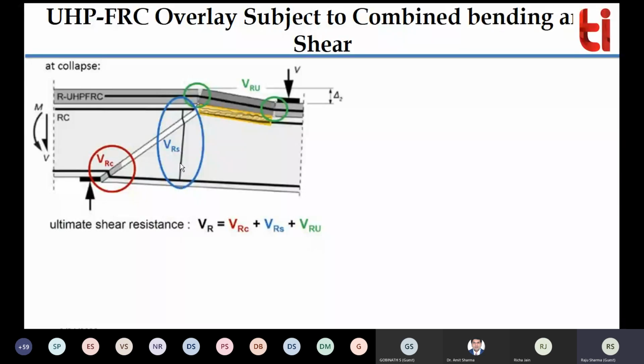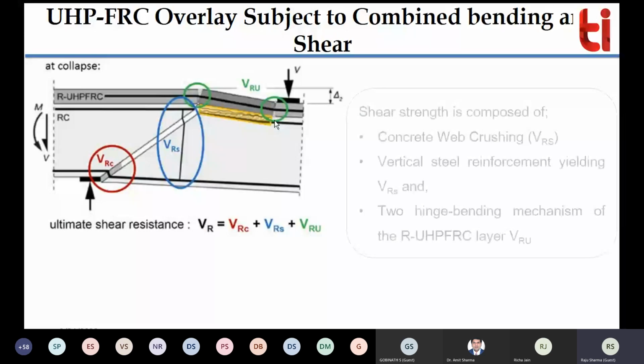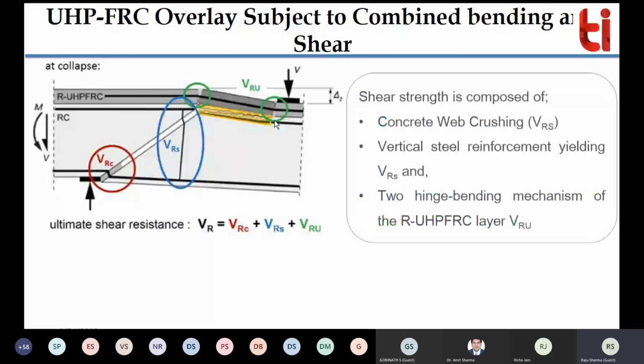Because of that, you can see that once the crack deviates and propagates in the vertical direction, towards the top compression face of the bridge, the crack path is deviated, shown in yellow color, because of the ultra high strength concrete provided on the top, right? It provides a kind of confinement to that crack. So the crack deviates itself and reaches towards the other side. So you can say you get a delay in the failure by using this kind of material, right? And your shear capacity will increase. So these are some of the points which I just explained to you, right?